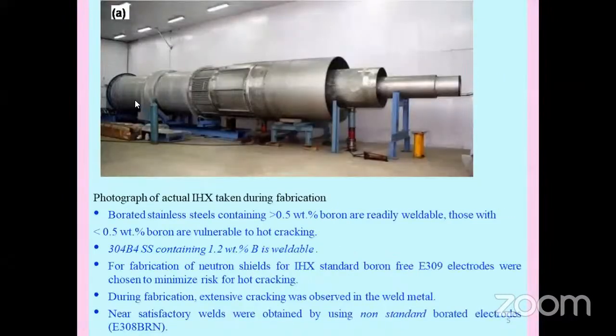So this is the photograph of the intermediate heat exchanger during fabrication. You can see it is a big structure, and this borated stainless steel neutron shield comes somewhere in this region, which is facing the reactor core. So generally the understanding from the literature is that borated stainless steel containing more than 0.5% of boron, that is, already I have told that this class of steels contain 0.2 to 2.8% of boron in it, the steels which have more than 0.5% of boron are considered to be more easily weldable than the stainless steel that has less than 0.5% of boron. In our case, 304B4 grade stainless steel has around 1.2% of boron. So it was considered to be fairly weldable.